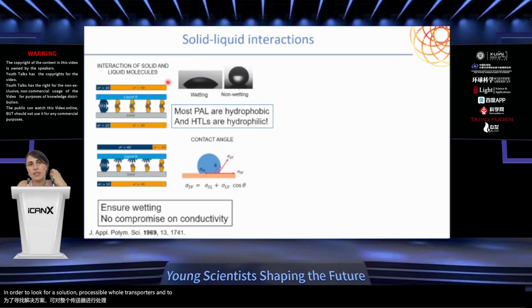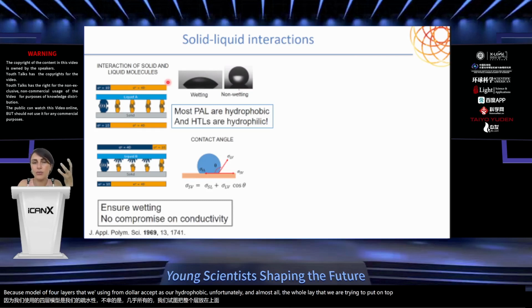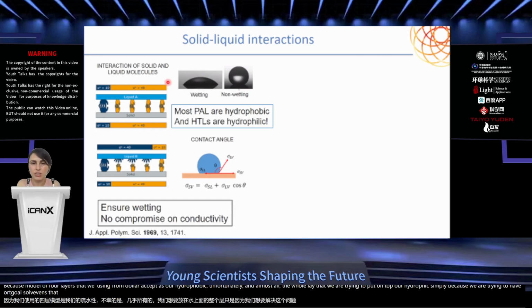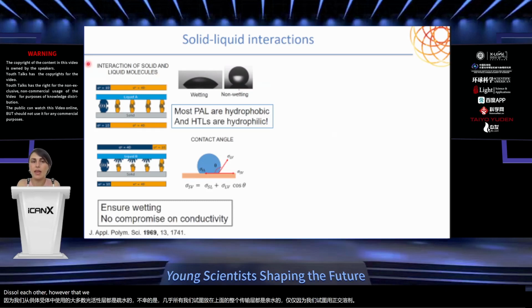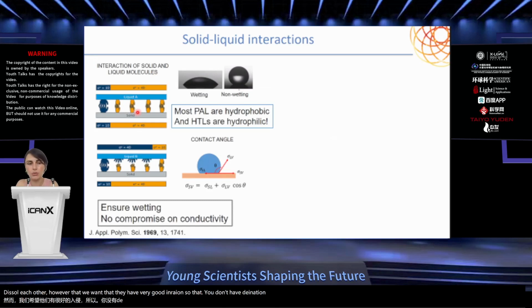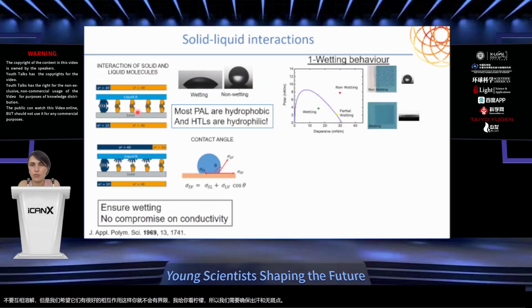And to do this, again, we are using the solid-liquid interactions and the solubility spheres, because most of the photoactive layers that we're using from donor acceptors are hydrophobic, unfortunately, and almost all the whole transport layers that we're trying to put on top are hydrophilic, simply because we're trying to have orthogonal solvents so that they don't dissolve each other. However, we want them to have very good interaction so that you don't have delamination, which I will show you in a minute. So we need to ensure this wetting and no compromise on the performance.